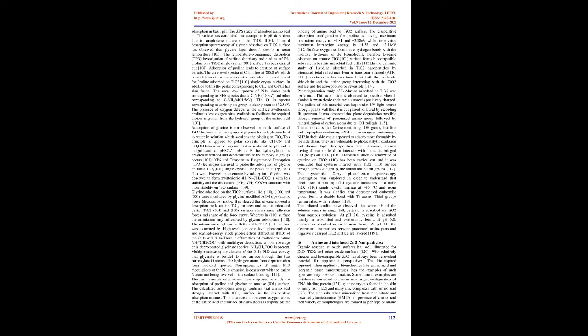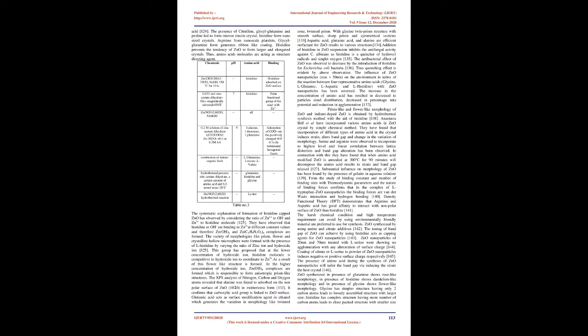A DFT approach was used to get insight into the adsorption of proline and glycine on the TiO2(110) surface. 102. As per this approach, the most stable configuration is an anionic moiety connecting two surface titanium atoms via the carboxyl oxygen atoms. The amino acid forms hydrogen bonds with the surface. Owing to the amphoteric nature of the TiO2 and the zwitterionic nature of the amino acid, the carboxylic group replaces the surface O group on the Ti site and connects to Ti. 103.